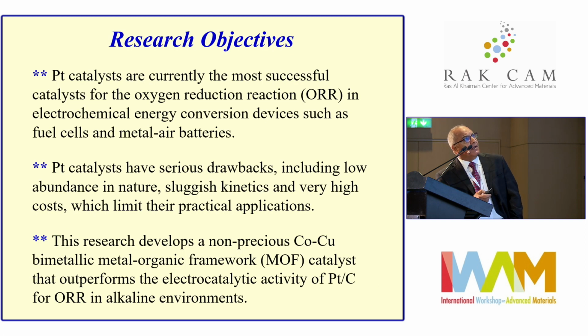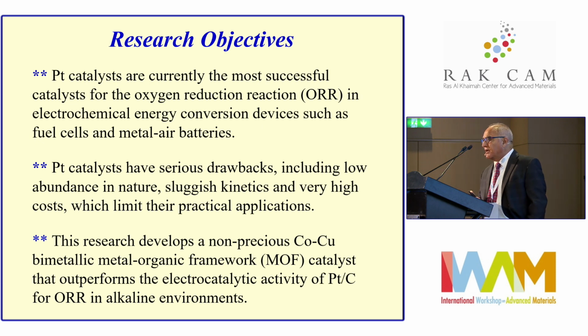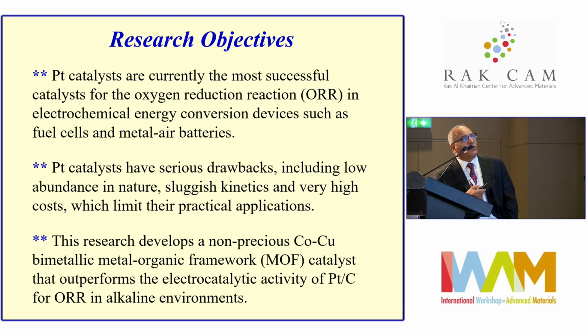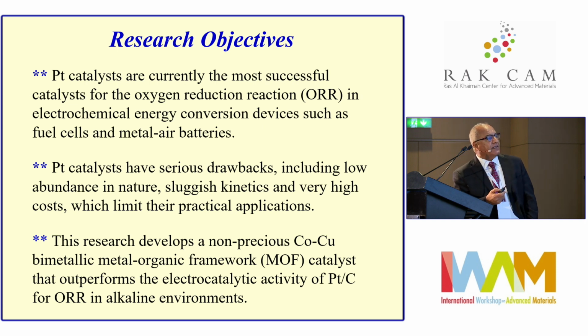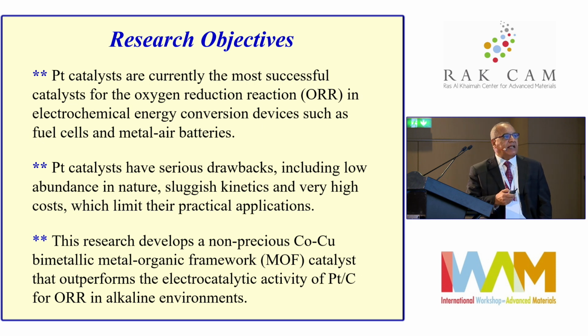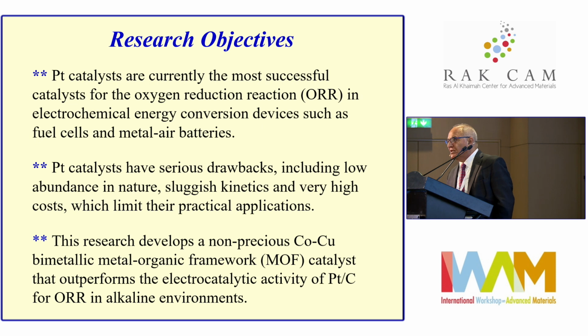So the objective, as I mentioned, is to replace the platinum catalyst, because platinum carbon is known as the benchmark for oxygen reduction reaction, which is very important, of course, for fuel cells and for many other metal-air batteries, like the zinc-air battery. This reaction is extremely important for any electrochemical energy conversion, including fuel cells. The platinum catalyst has several drawbacks, including, of course, low abundance, very slow kinetics, and very high cost, and everybody is trying to get away from using platinum as a catalyst for this reaction and also for other reactions.